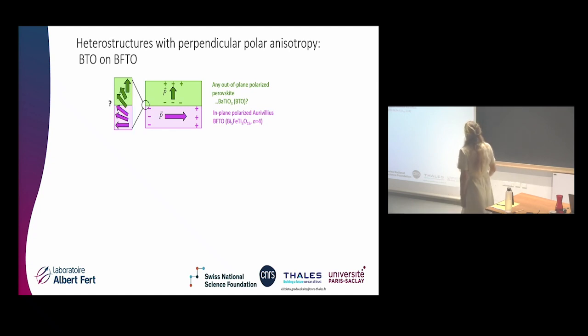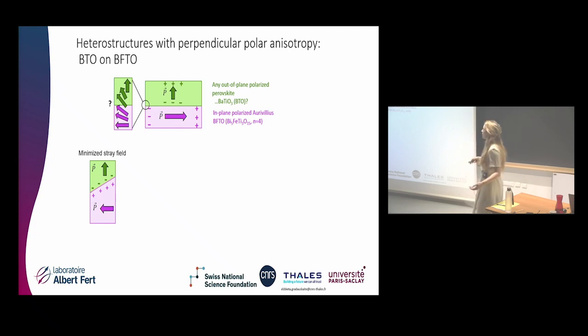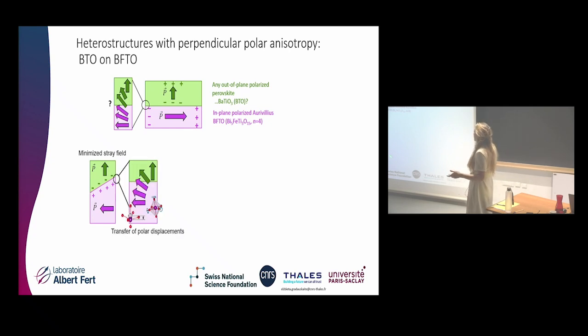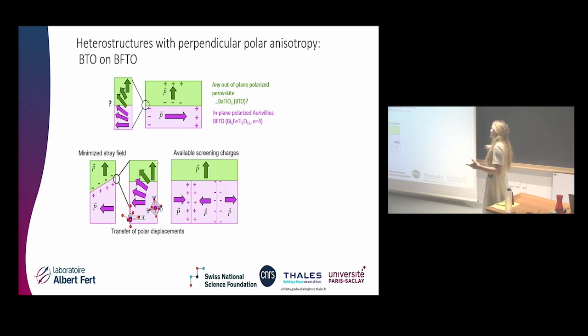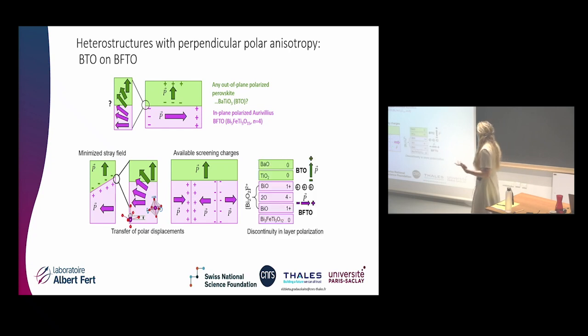What we can expect, there are many things. So first of all, of course, there's some minimized stray field. There will be some transfer of polar displacements because we already know the bottom layer is ferroelectric. There will be some available screening charges at the domain walls that will potentially screen it. And quite, I would say, maybe even most importantly, we have to think about the layer polarization, or essentially the charges that we have on the atomic planes.